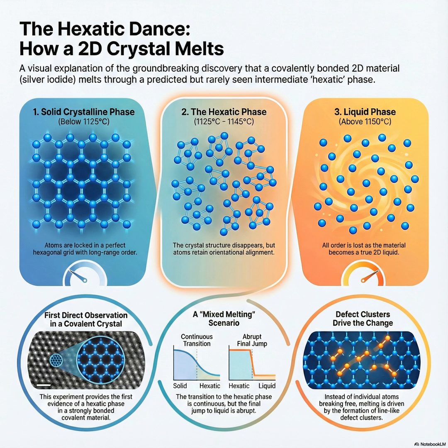Okay, so we've confirmed the hexatic phase exists. Now for the final showdown, KTHNY versus the mixed melting scenario. We know solid to hexatic was continuous. But how did it go from hexatic to liquid? To figure that out, you have to look for coexistence. A continuous transition means the entire material transforms uniformly, gradually. But a first-order transition means two distinct phases, hexatic and liquid, suddenly appear and compete for space side by side.